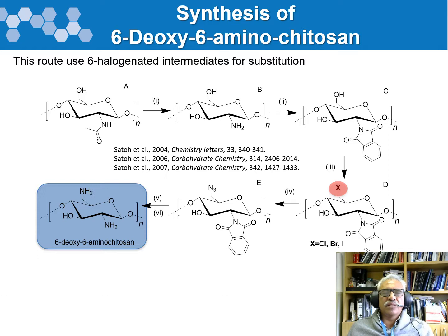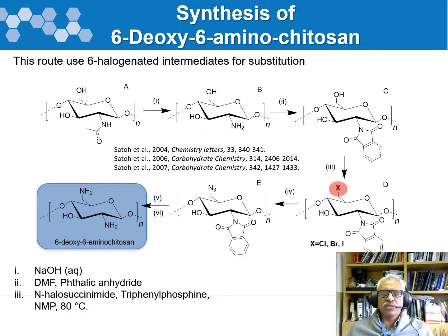In earlier studies, with the chitin itself, you first do a base treatment, sodium hydroxide aqueous, that will take care of the acetyl group here. Then the second step is to protect the amino group with a phthalate group, and then you want to convert the hydroxy into a better leaving group. There are many ways of doing that. In this particular way, they've taken N-bromo, N-chloro or N-iodosuccinimide along with triphenylphosphine in N-methylpyrrolidone as a solvent at 80 degrees.